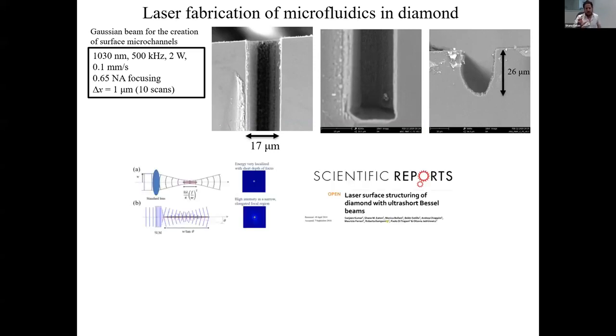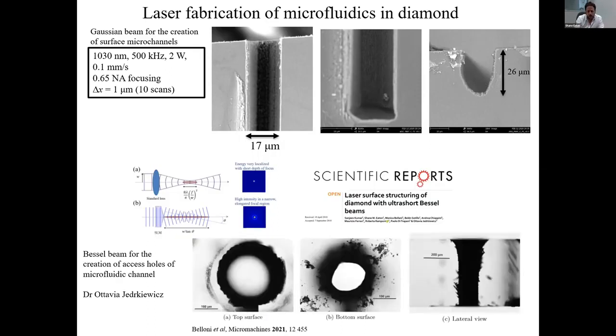And in addition, since we need to combine this with microfluidic tubing external to the chip, we'd like to have through holes which are connected to microfluidic tubing. To form these through holes through the 500 micron thickness of diamond, we propose to use Bessel beams. This is work done in collaboration with Octavia and Como. And Bessel beams, compared to Gaussian beams, have the advantage of a much longer, more elongated focus, which is ideal for forming these extremely high aspect ratio modifications. And in fact, we demonstrated through holes in diamond. This work was recently published, I think a couple of weeks ago, along with Ottavia.